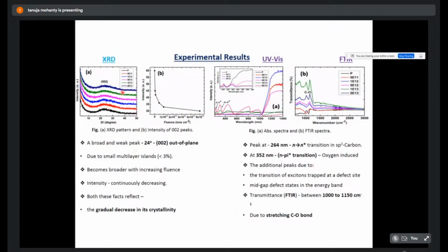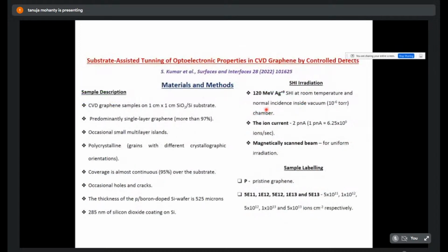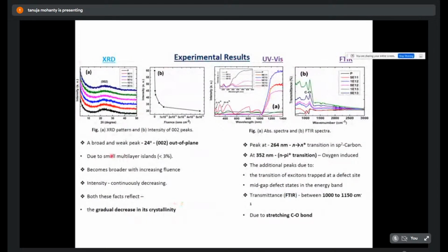This work is one of my students' work. It is in Surfaces and Interfaces. So what are the changes here? There is a change in the XRD peaks. In XRD, you have the pristine sample, and there is a broad and weak peak due to small multilayer islands, which become broader with increasing fluence. Fluence means the number of ions per second, that is flux, multiplied by time. That minimum this much of ions per centimeter square per second should be incident. If I increase the time, then that means I am increasing the dose. So there is a gradual decrease in the crystallinity, which is expected here.